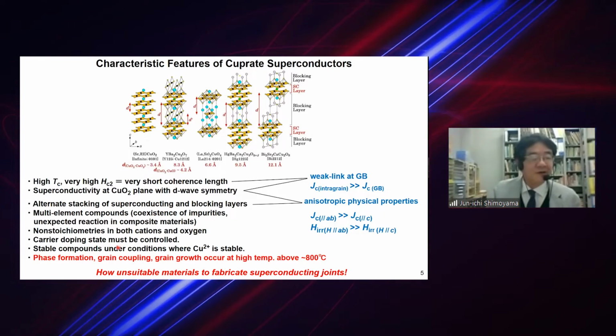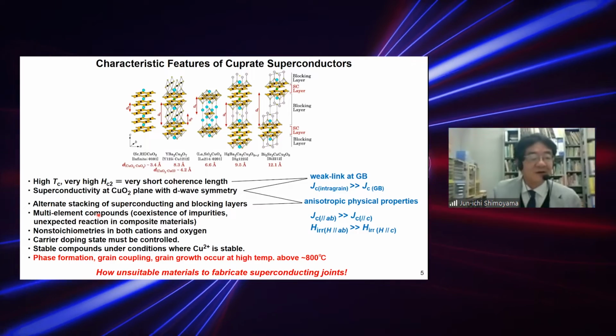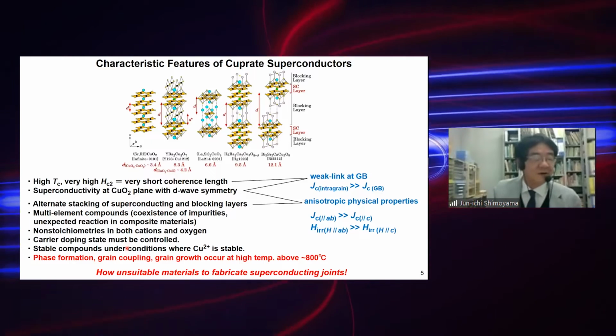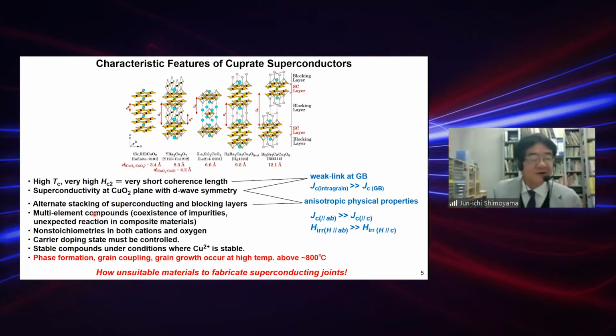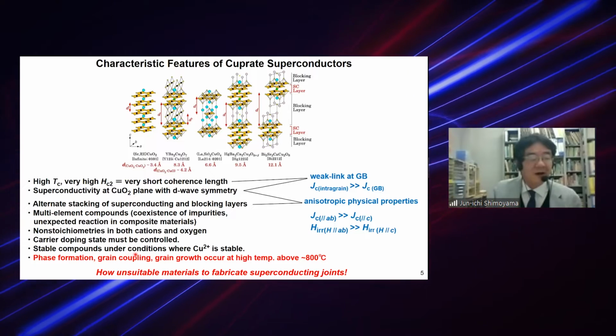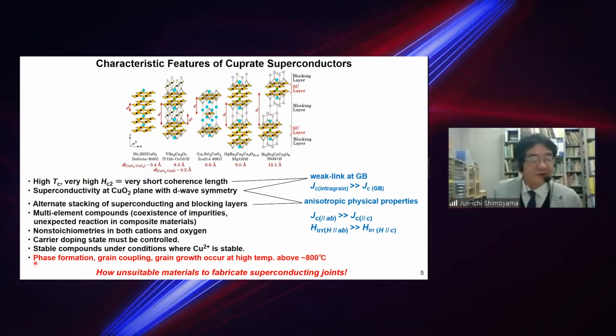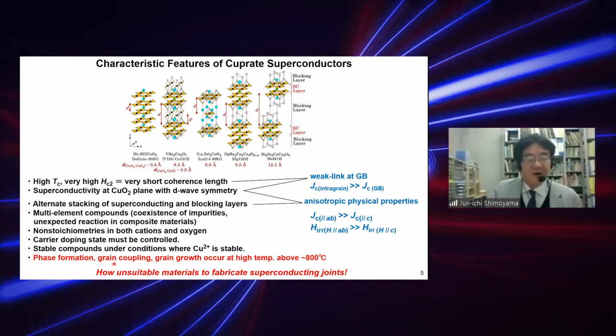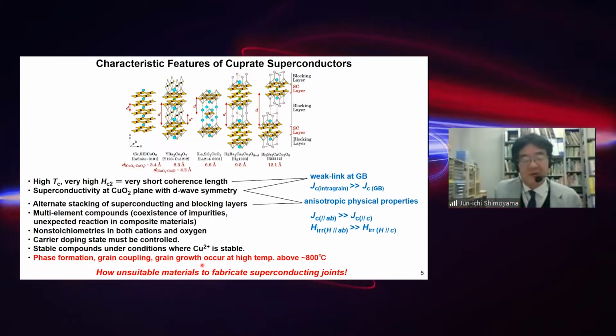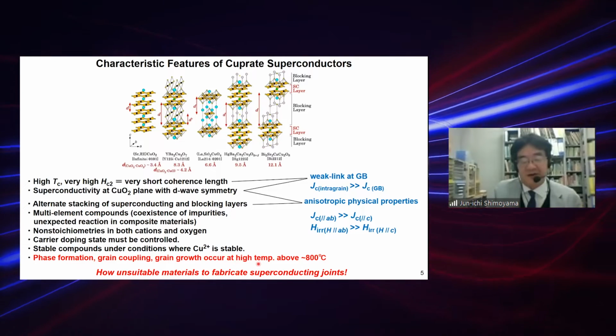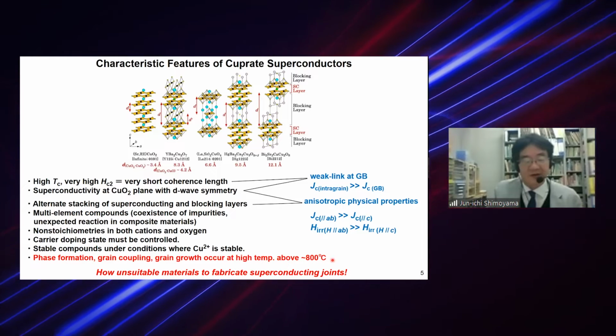Many other characteristic features of cuprate superconductors are listed here, but the important point is that phase formation, grain coupling, and grain growth occur at very high temperature, above 800 degrees C.